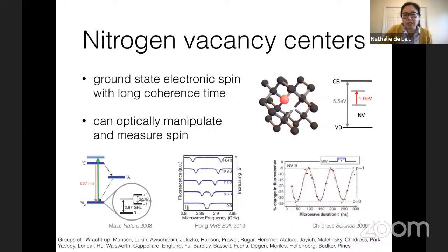So the nitrogen vacancy center in diamond is a point defect that consists of a substitutional nitrogen next to a vacancy in the diamond lattice. And it turns out that this defect gives you extremely deep electronic levels inside the diamond band gap. If you look at the valence band and conduction band extrema in diamond, the ground state for NV is something like halfway between these two band edges. And then you have enough headroom, given the very wide band gap of diamond, that you even have room for excited orbital states that are very, very far away from these band edges. So to first order, you can really think of this as a trapped molecule, where you think of linear combinations of atomic orbitals giving you molecular orbitals, and you don't have to consider the continuum of states from the band structure of diamond.